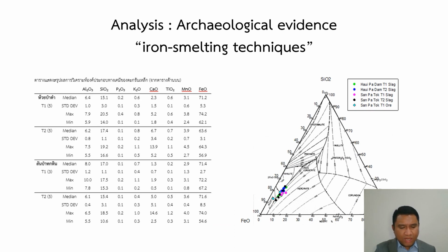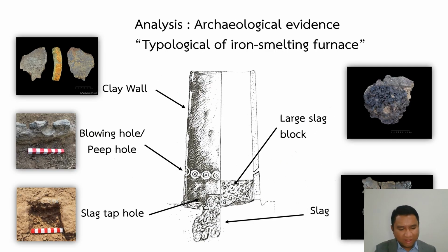According to the handheld XRF analysis result, the smelting temperature of both sides is about 1150 to 1300 Celsius degrees. The smelting technique is the direct process. The type of furnace is a shaft furnace made from purely clay. The diameter is 70 to 90 cm and 150 to 180 cm high. It has boring holes surrounding the middle of the furnace body and 4 slag tap holes on the bottom of the furnace.